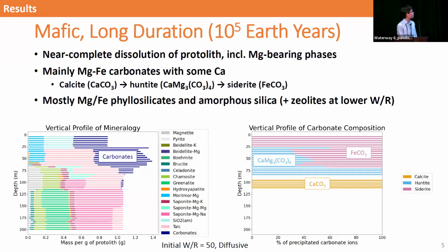Next, we look at the mafic protolith with a long duration of alteration. The protolith was almost completely dissolved, and the resulting carbonate composition was mostly magnesium iron carbonate with some calcium content. There was an evolution of carbonate composition from calcite to huntite, and then gradually replaced by siderite. And the associated secondary silicates included magnesium iron phyllosilicates, amorphous silica, and zeolites.